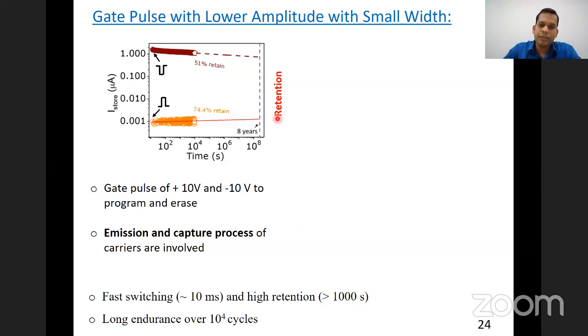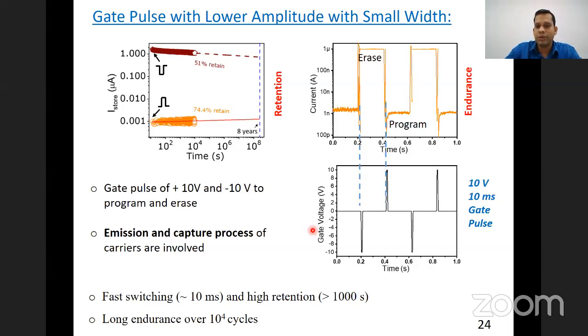The retention analysis shows that if we program and erase the state, we can even wait until 8 years, and we can retain the information almost more than 50%. So it has good retention, and the endurance we have studied until 10^4 cycles, with very good reproducibility of the erase and program states. Of course, there is an emission and capture process going on in this, so that we get a slow decrement and increase in both. That cannot be neglected as well.